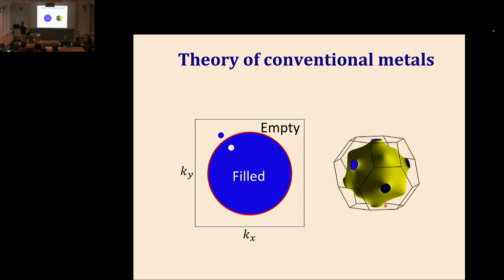This is the Brillouin zone, and this surface is the Fermi surface. So the low energy excitations of the system are described in terms of almost independent particles, quasi-particles, with modified parameters, with a new effective mass. These things live for a finite amount of time. They're not actual eigenstates of the Hamiltonian, but as you approach the Fermi surface, as you go to lower and lower energies, they become better and better approximate eigenstates of the Hamiltonian.